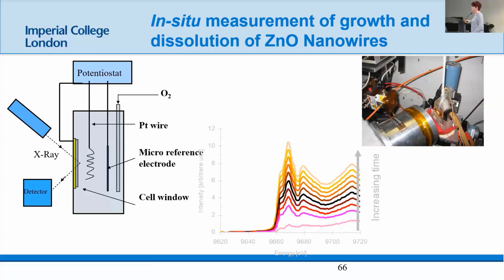And what you see is actually not very exciting for a set of X-ray absorption spectra, because nothing changes. It deposits, it goes from zero, there's nothing on the surface, right? So I get no signal. And then as I deposit, I see these zinc oxide spectra, and they don't change at all over time, right? So I'm depositing zinc oxide and it's staying as zinc oxide.